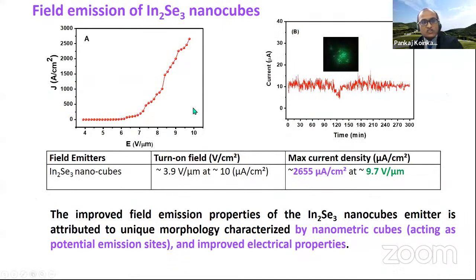We have studied field electron emission, which is an optoelectronic property, to see whether this material can be used for display devices, that is, field emission display devices. We have observed that this material can produce a current density up to 2655 microampere per square centimeter at 9.7 volt per micrometer. So this much electric field is required to draw the current density from these nanocubes. This is a high current density as compared to other available materials.